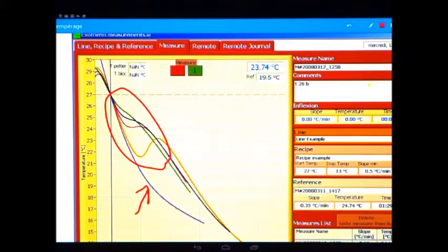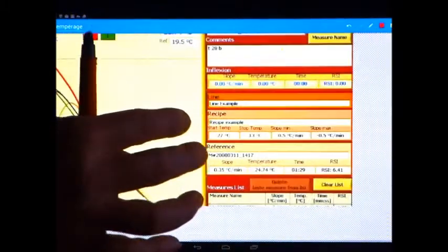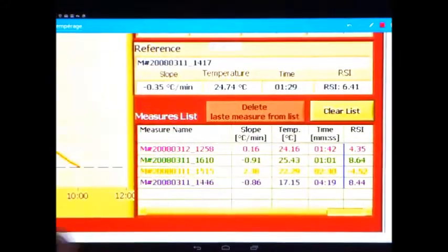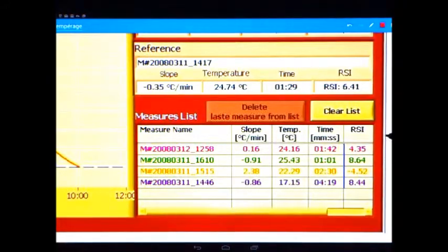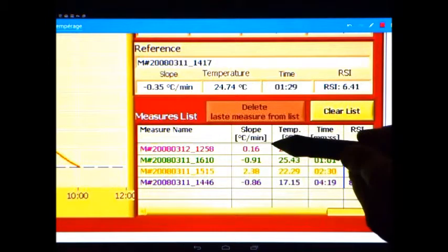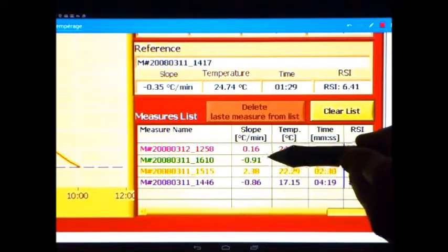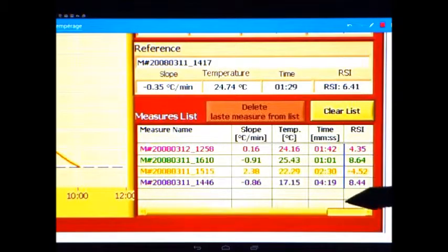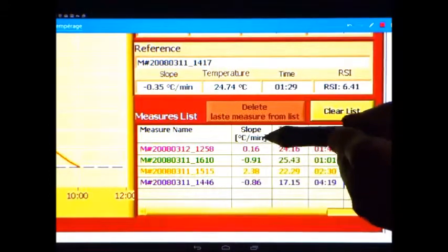Most tempermeter manufacturers offer an index calculated with the slope of the curve. It was thought to help better understand the relationship between the curve and the amount of crystals formed in the tempering step. Have a look at the index. Could be called RSI, TI, depends on the manufacturer. And you have the slope. The index is calculated out of the result of the slope.